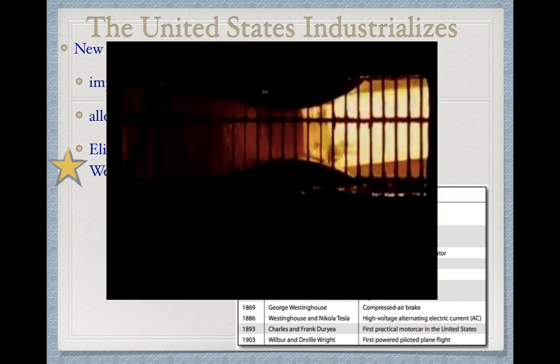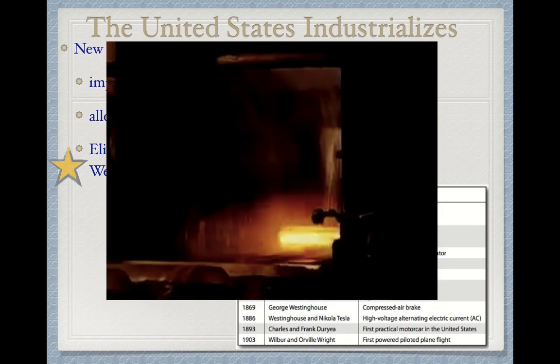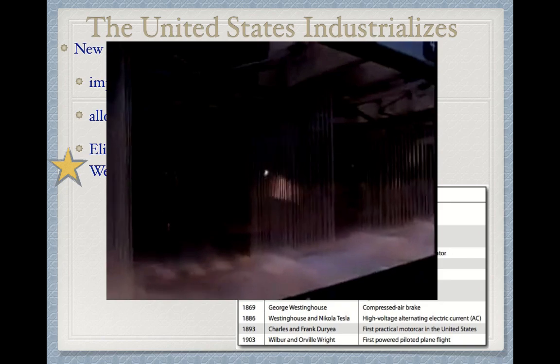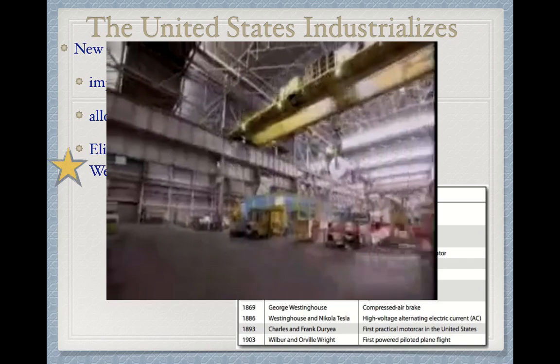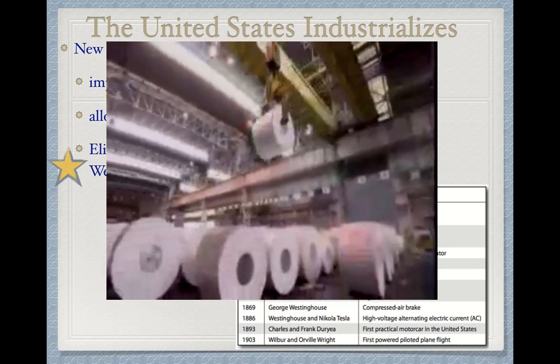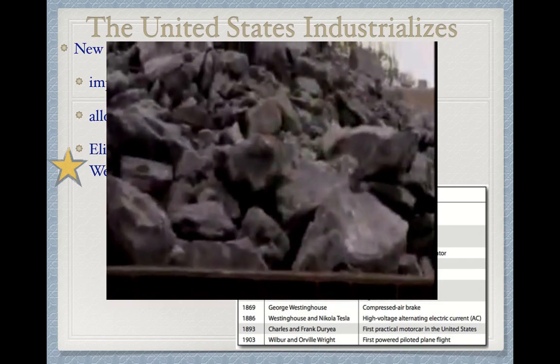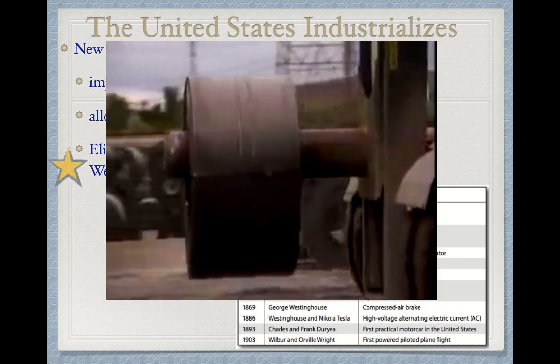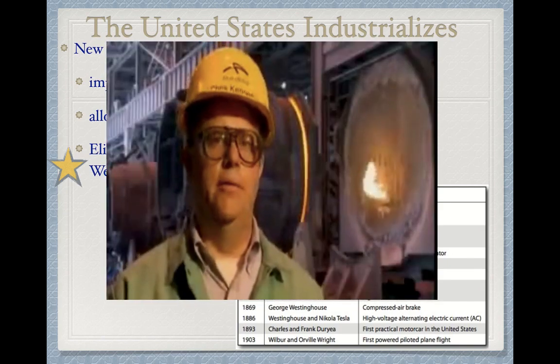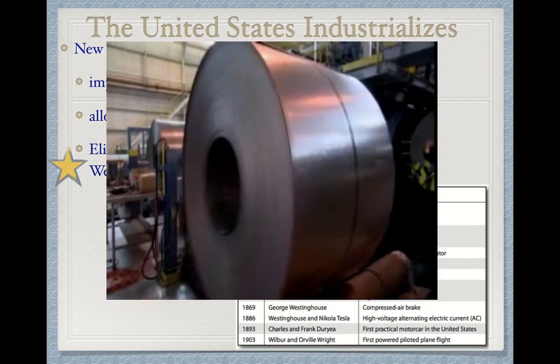But the steel is still red hot, with a temperature over 1,000 degrees. So the metal is transferred to a series of casters and rollers, where it's cooled with water and reduced from 75,000-pound 9-inch slabs to a ribbon just 3/4 of an inch thick. The entire furnace process takes just 2.5 hours to turn the natural mined substance of iron ore into the world's most widely used high-strength metal. We're very proud. Without us, a lot of stuff can't be made.